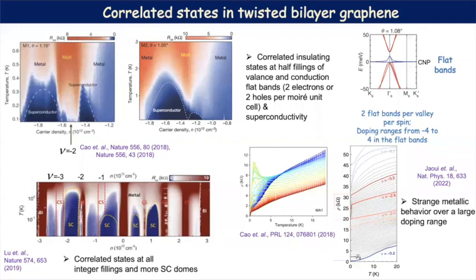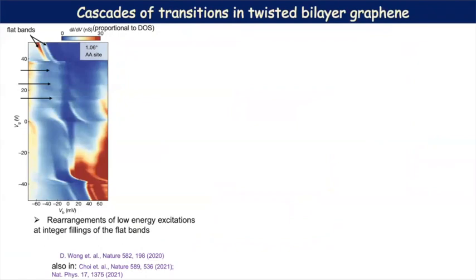Now, the specific experiment which directly concerns our results is this cascade of transitions in this system. So here I have this color map, which is from an STM experiment. And this is a derivative of current with respect to voltage, which is proportional to the density of states. So in the y-axis, I have the gate voltage that tunes the doping, and in the x-axis, I have the bias voltage. And here you can see the peaks from the flat bands when the chemical potential is here, when the flat bands are filled.